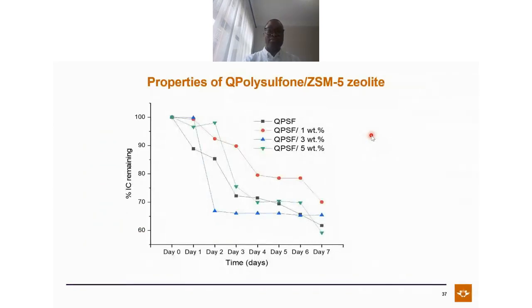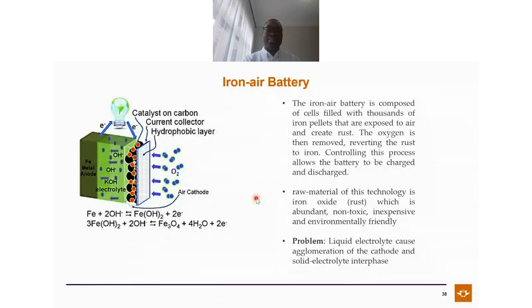We look at the degradation of the membrane. If you can see the membrane, it was able to withstand from 100% after 7 days. You can see the one with nanomaterial, they were able to retain above 60%. Also with the one without material. So this is good. And also this, we still want to do it over 2 or 3 months and see how it performs. Another one, the last section of our presentation is the iron-air battery.